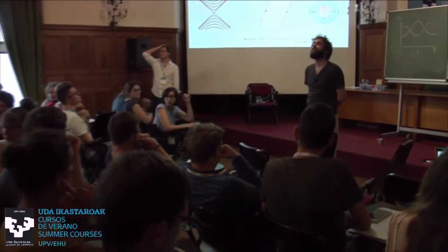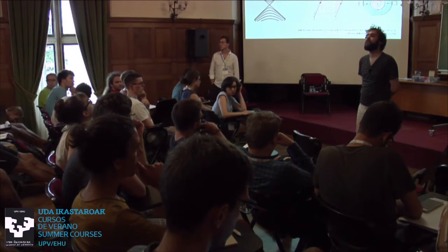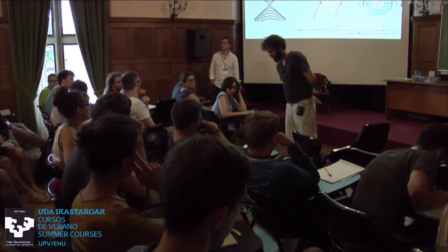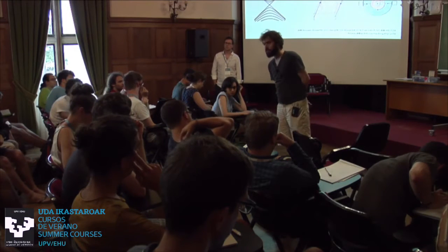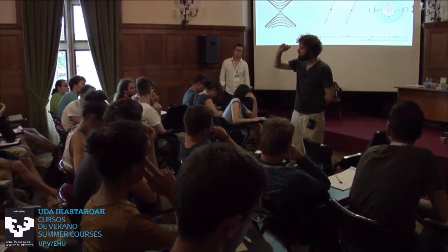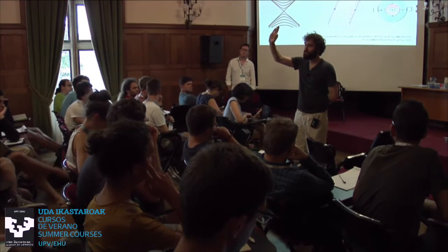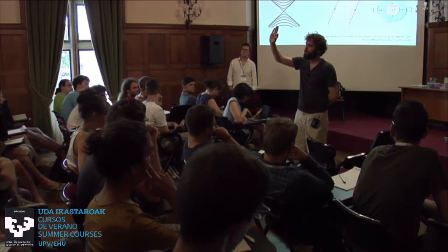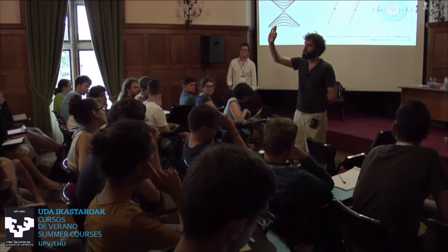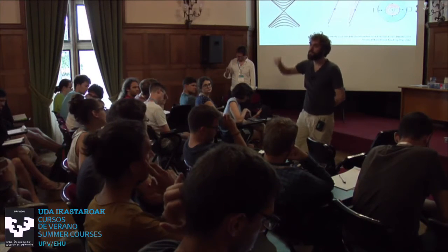Your model is fine-tuned. You have to fine-tune the magnetic flux to get the Dirac state in the nanowires. How sensitive is it to the deviation from the pi flux? It's not very sensitive. And the reason is basically that it's true that to have a zero gap, you need to fine-tune it to be pi flux. But then the size of the gap that you generate by being a little bit off depends on how far off you are, and it doesn't immediately become very large.